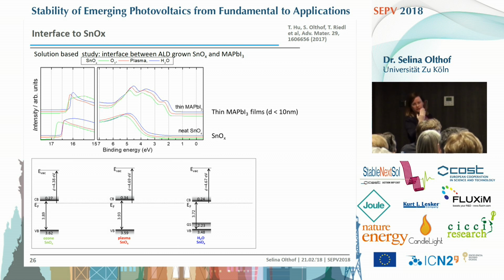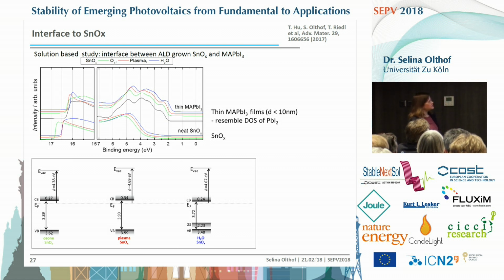They're slightly shifted in energy, so something changes with respect to the extraction layers. But what is weird is that this does not look like perovskite. This looks like lead iodide again. So the black curve here that just showed up, this is how lead iodide looks like in UPS, and you can see this is just the same. And we did XPS measurements as well that I'm not showing now, but here again we are missing nitrogen, we are missing carbon, so the MAI fully dissociates and leaves the surface, even in the solution processing, and all we have left is lead iodide.